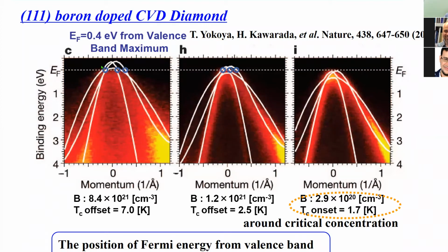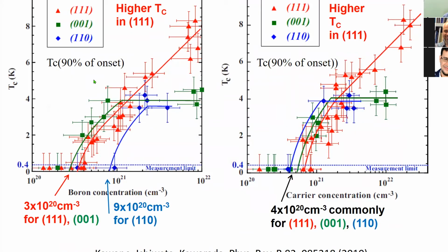This film surface is also very important for explaining the mechanism of superconductivity in diamond. So we repeated the French group's work on a different substrate. The French group normally used the 001 surface at that time, and we used 111, because on the 111 diamond surface boron can be incorporated very efficiently, allowing the superconducting transition temperature to become higher and higher.